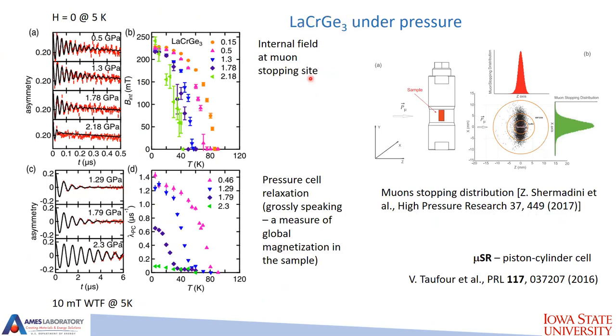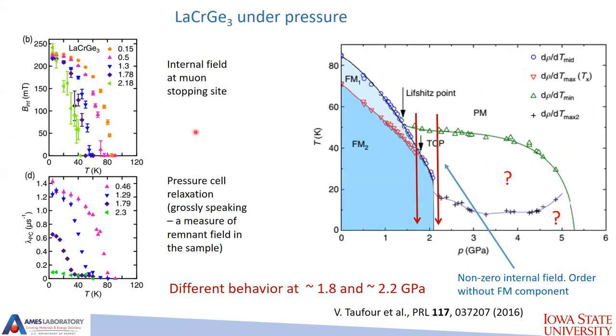In collaboration with Rustem, we did muon spin rotation under pressure. I will not go into details of the technique, but basically there are two things we can do. We can look at the internal field at the muon stopping site or sites. Or we can look at the signal from the pressure cell, which, grossly speaking, is a measure of how strong the global magnetism of the sample is. You can see that muons stop not just in the sample, but in part of the pressure cell. And if the sample is, for example, ferromagnetic, there are stray fields going into the pressure cell, and these muons will feel the field. So let's look at these two plots a little bit more carefully.